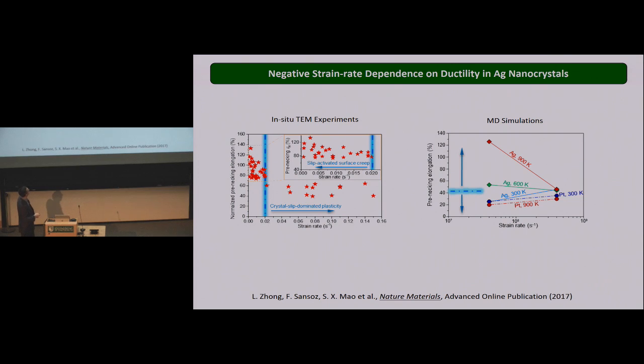And so something comparable we found is in the in situ TEM experiment. By reducing the strain rate, we find the ductility increases. And that's totally abnormal. Usually, when you decrease the strain rate, you will break these wires faster. The ductility should drop. And that's not what the experiment shows here.